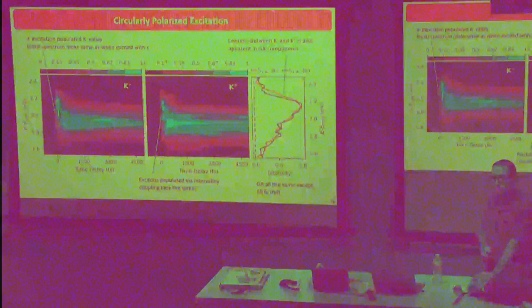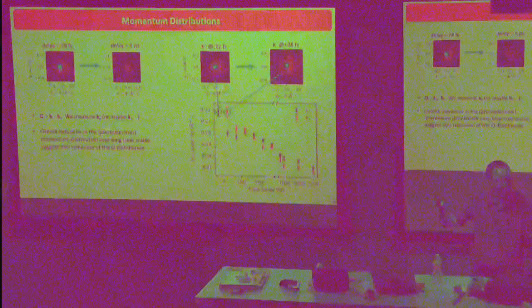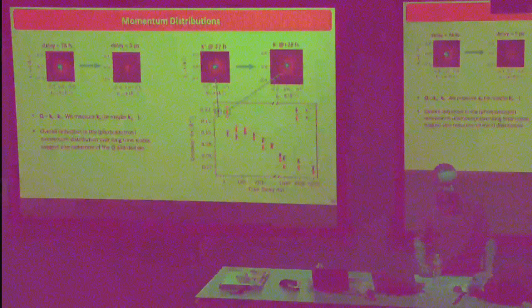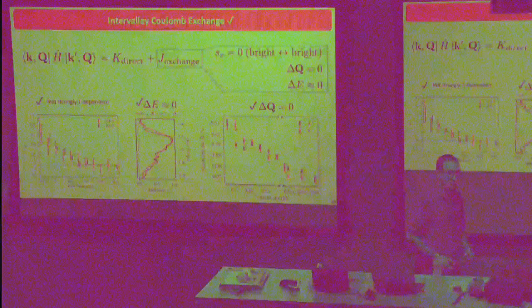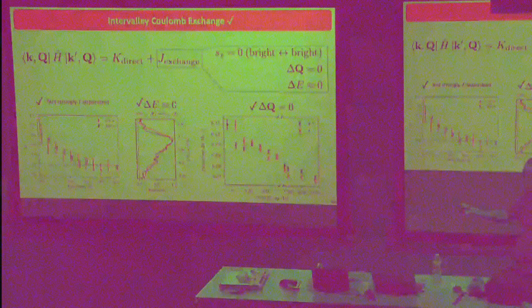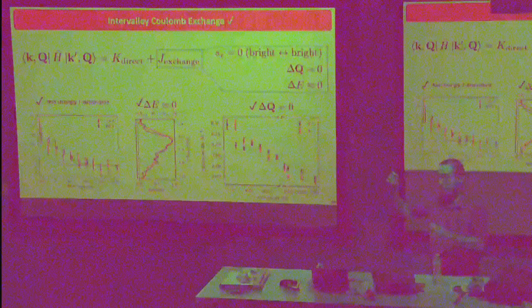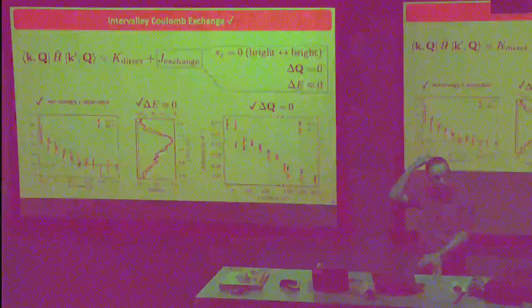We're ruling out phonons as the primary driver, but one could argue you could still have phonon involvement. If you had phonon-assisted transfer you would expect the energy to shift down by an optical phonon energy, which is 50–100 meV in these materials — something we would likely see. The exchange interaction of a few meV sets a picosecond time scale at small Q, but tens of meV at high Q gets you into the 50–150 femtosecond world. So the 50-femtosecond scale is consistent with exchange interaction at high Q.